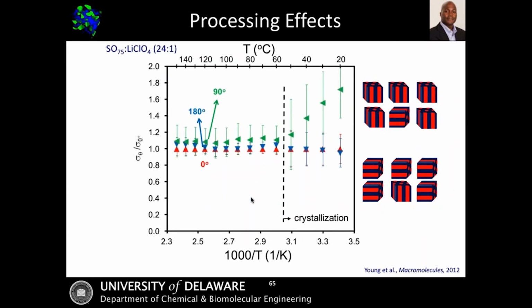So how can we get around that? In this particular case, we've made another sample. This is a cylinder-forming block copolymer, but in this case, the blue is actually the conducting domains. You can see that the blue domains are co-continuous through the material. So if I look at 0 degrees, or rotate it 90 degrees or 180 degrees, in all cases my conductivity is nearly identical. Again, it's at 1.0 because we've normalized it to the 0 degree point, but this conductivity is actually about a factor of 3 higher than the conductivity you saw on the previous slide. So by incorporating a co-continuous structure, not only have we improved the conductivity, but we have also been able to eliminate processing effects in these materials.